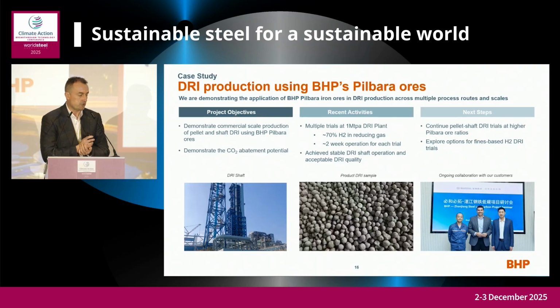In terms of those DRI shaft trials, we've been successful working with our partners in China to complete full-scale tests around 2 weeks at a time using Baowu's Zhanjiang steel, which is around 1 million tonnes per annum scale. Basically using a pellet blended with different hematite and magnetite with our Pilbara iron ores, and the DRI shaft operation was smooth, DRI quality was good, and it was able to be blended into the BOF with hot metal and scrap. So a good outcome, and the next steps really are there to take that Pilbara ratio higher in the pellet and then do the same sort of commercial scale trials.